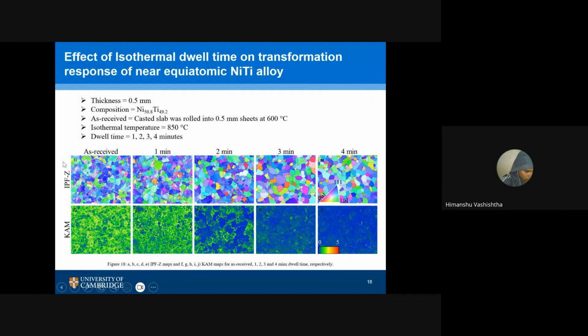Here is the IPF-Z map - you can see there is no heterogeneity in the material. The orientation is almost the same for all the specimens. All these 4 coupons or samples are different - it's not like I took one sample, heated it for a minute, characterized it, then heated the same sample for another additional minute to make it 2, then characterized it. It's not like that - we have taken 4 different coupons to see how it behaves.